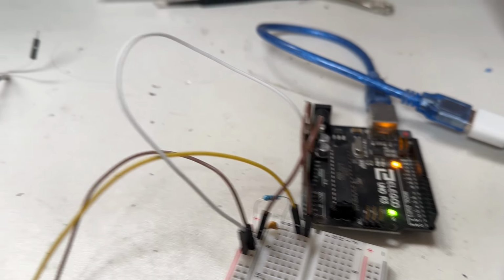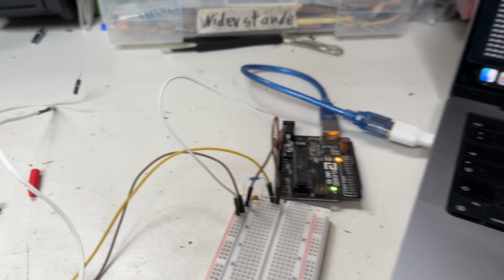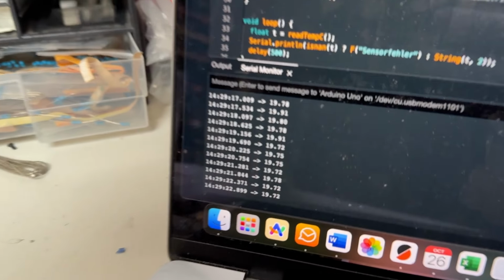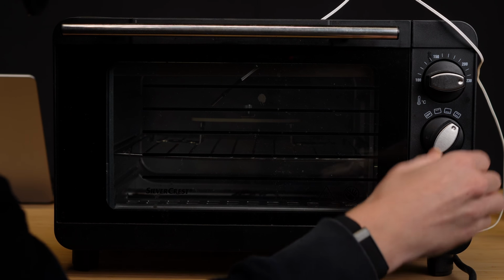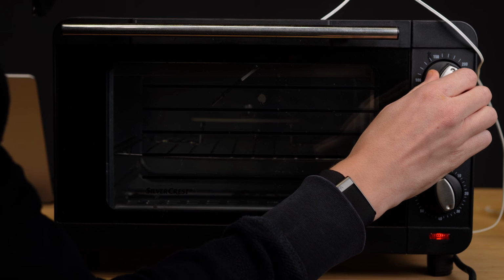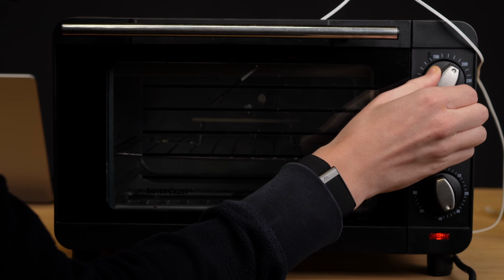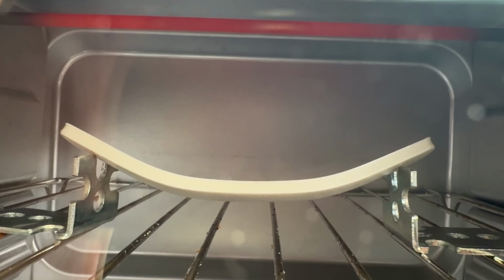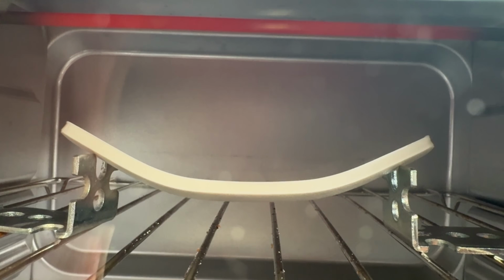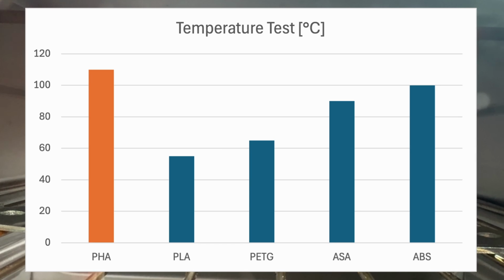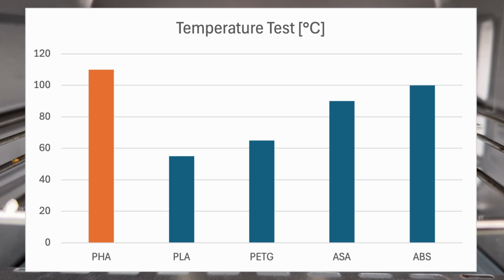For the first step, I used such a NTC100K to measure temperature with an Arduino. For the test, I put a sample between 2 holders into the oven and made it heat up while measuring the temperature. I measured 110 degrees C when the sample failed under the load of the screw. This value is very good, similar to that of ABS and ASA.